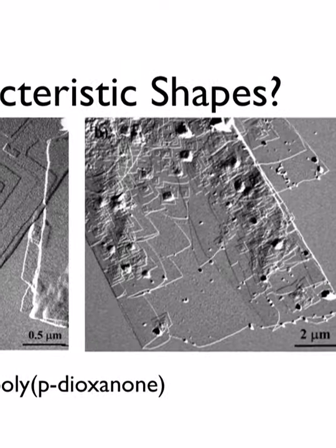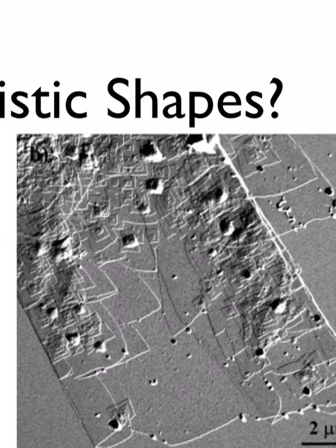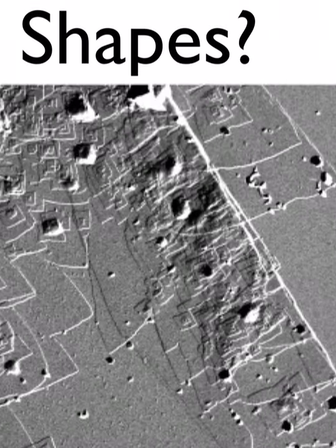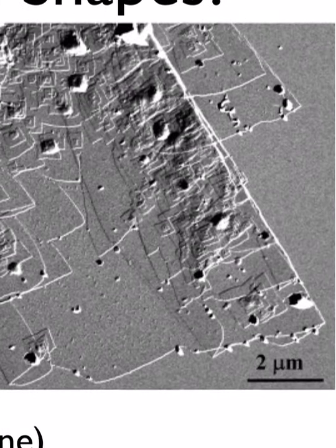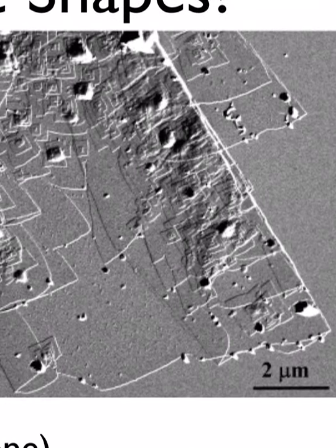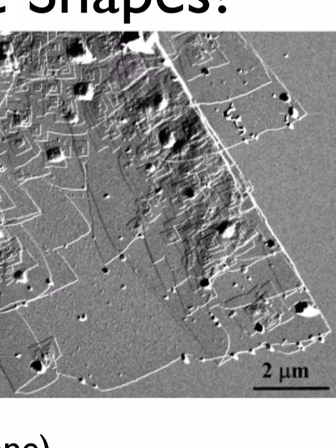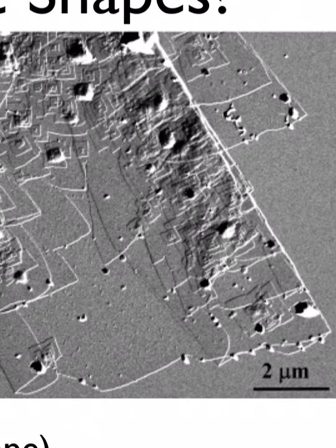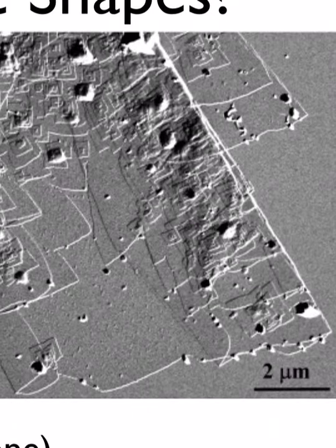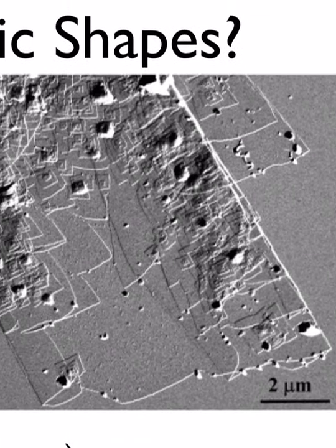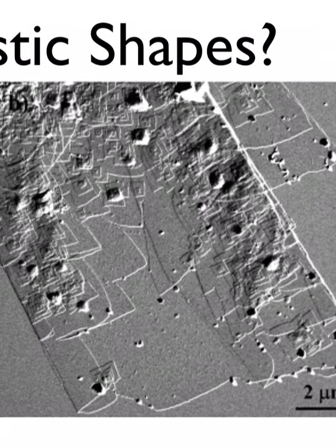In some cases, you get large crystals, and on top of that, you get a bunch of smaller crystals. All right, and going zooming out here, that's a 2-micron bar. So you can start to see that even in solution, we get some really tiny crystals. So we're getting these submicron, maybe in some cases 100 nanometers, and this is under the best conditions. This is in solution, a little bit higher concentration, but still in solution. And so in the melt, things are even worse.